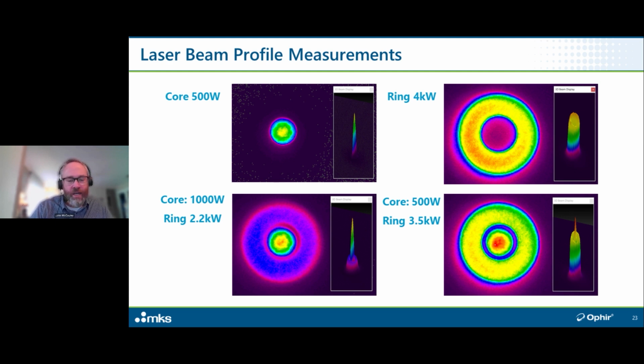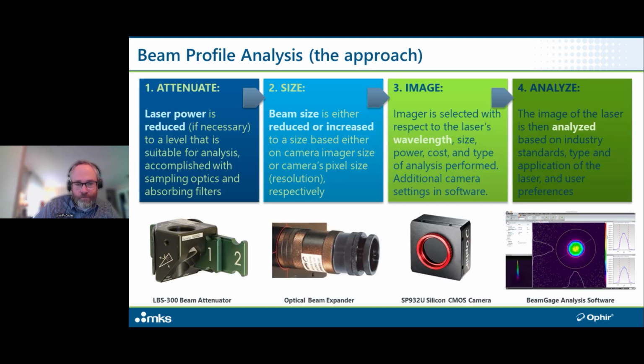Additionally, at the bottom, you've got some shapes that further illustrate this idea of power density. You've got the core at 1 kilowatt and the ring at 2.2 kilowatts. You see the core is obviously a smaller beam size, and even though it's at a smaller power level, you get a much higher intensity, much higher power density. And in this bottom right image, you've got the core at 500 watts and the ring at 3.5 kilowatts, with roughly the same intensity. The core is a little bit higher in power density, even though it is at a lower laser power.